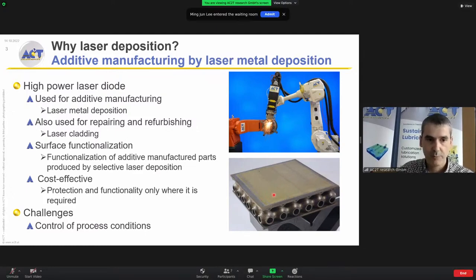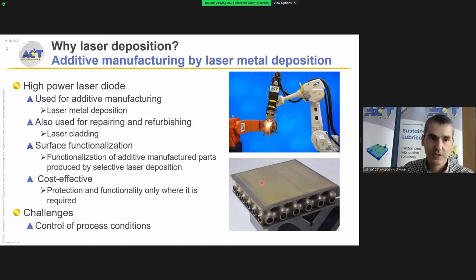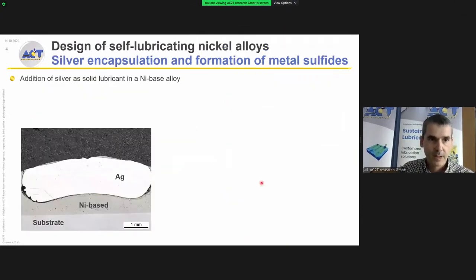It's a novel manufacturing approach, but it also has some challenges in the material deposition. The point is that, for example, if we have a nickel-based alloy and we want to make it self-lubricating, we need to add some solid lubricants. For example, silver is a soft metal with low shear properties, but nickel and silver are not miscible. So if we melt them with a laser, we end up having some microstructure like this. It's a substrate with a nickel-based coating with a huge silver bubble on top of it. So this is completely useless. It's just a fancy way of wasting silver.